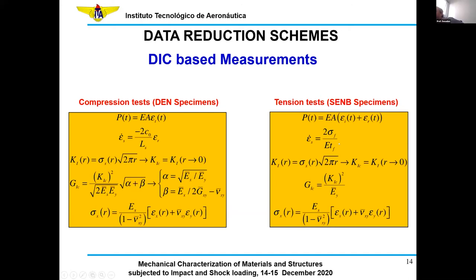In a similar way, by using the same specimen, we can compute the load at the vertex by using the dynamic equilibrium equation. In this case, the force depends on the incident and reflected pulses that were measured by the two pairs of gauges that I mentioned before. With the failure stresses, by using this configuration and the thickness and the time of failure, we can compute the strain rate and the stress intensity factor, in a similar way as applied for the damaged specimen.